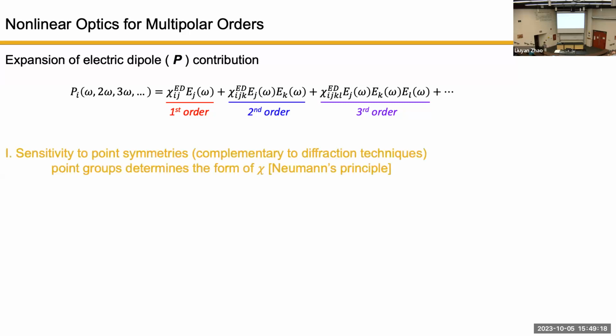Okay, and it has good benefits because I have the incoming field and the outgoing field. This tensor really represents the material's information that is bridging the incoming and outgoing fields. One property that is prescribed by Neumann's principle is that my material's tensor has to obey all the symmetries of my material since it's describing it. If my material has threefold rotational symmetry, my tensor should obey that. So whatever is imposed from the material happens in this mathematical tensor. Then you can use the constraint from the material to define the tensor's form. If I have a high rank tensor, then I have more elements for me to discern many different symmetries. So going to higher rank processes gives us this benefit of seeing the symmetries with more sensitivity.